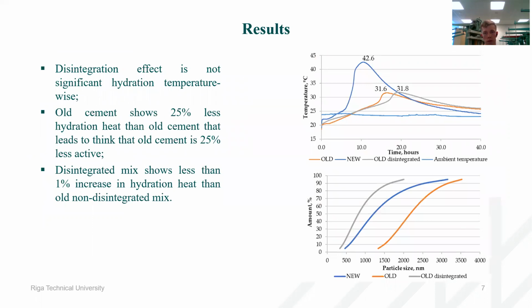So the results from the semi-adiabatic results, you can see that new non-disintegrated cement mortar showed significantly higher hydration temperatures. In this case, it's 25% bigger than the non-disintegrated and disintegrated old cement mortars. As for the old non-disintegrated and disintegrated cement mortars, the hydration temperatures are similar. The peak values are within 1% difference. Therefore, the disintegration doesn't bring the cement activity back.